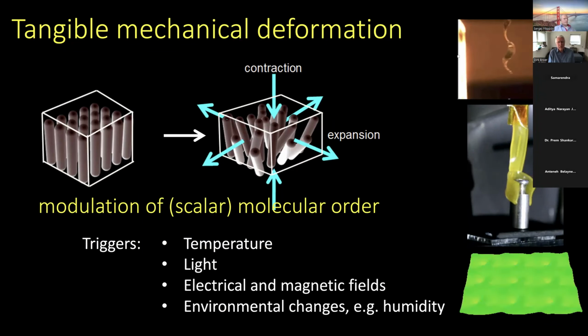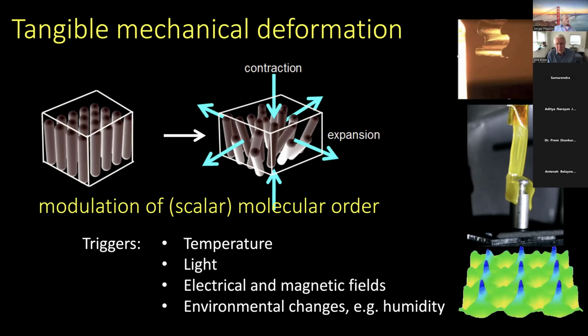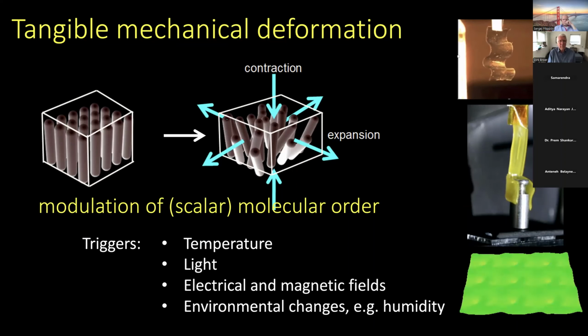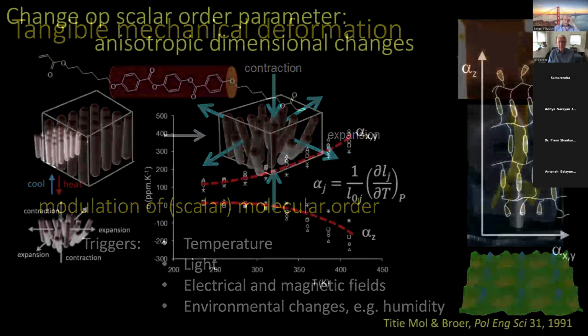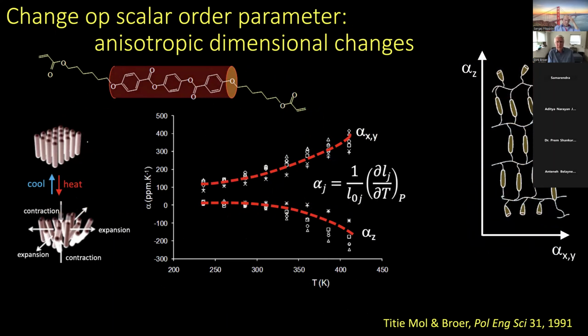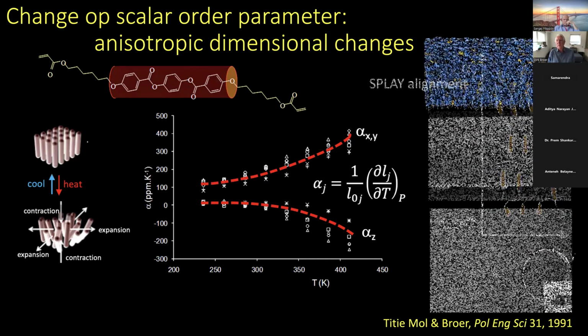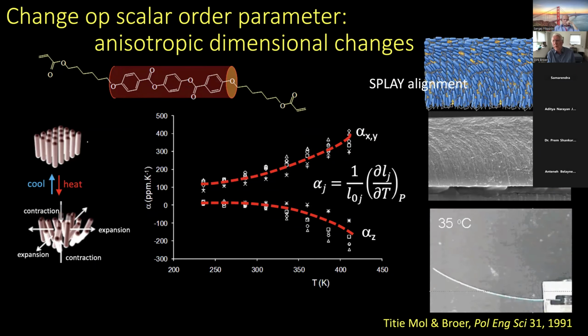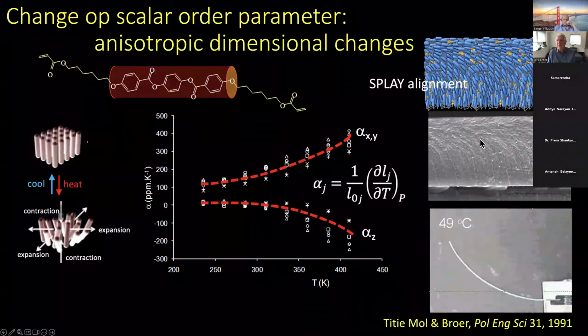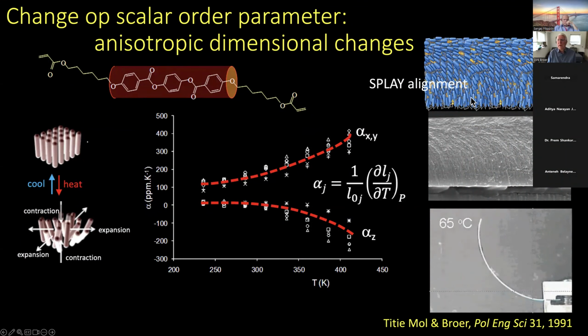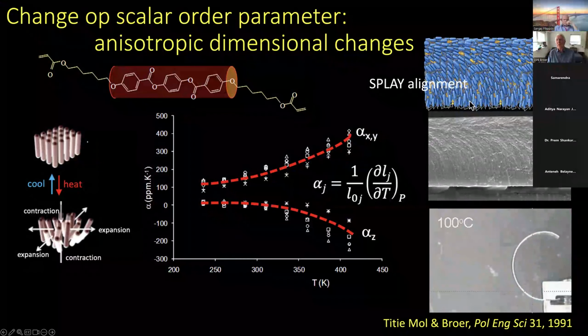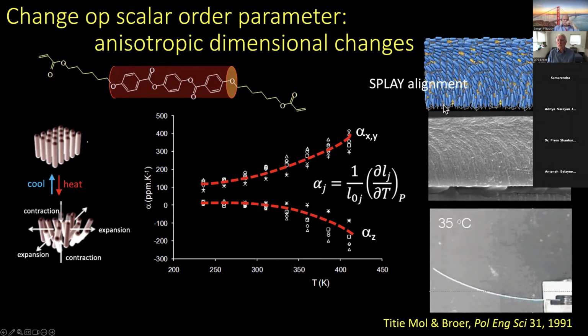So this is moving more and more towards the soft robotic application. And typical triggers are temperature, light, electrical or magnetic field, and the changes in the environment, such as humidity. And as said, the mechanism is comparable to that of the negative thermal expansion coefficient, change of order parameter, which means that if you, for instance, create a film, a thin film, where you have a splayed alignment, and with splayed alignment, I mean a parallel alignment at the top and a perpendicular alignment at the bottom. You can easily create this by playing with the interfacial conditions when you are making the films.